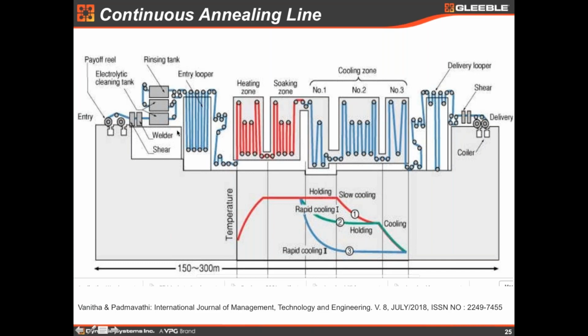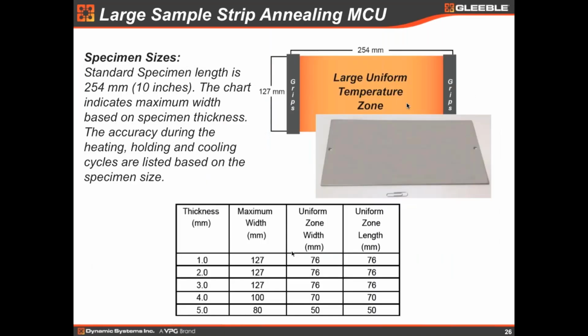So of course you don't want to sacrifice all this big amount of material, and you want to understand what's going on, so you can calibrate your heating or thermal cycles, both heating, soaking, and cooling zones. This should be tested and calibrated, but offline, not in the line, because that would be a production disaster. So what we do, you can use a Gleeble, a large sample strip annealing mobile conversion unit, and